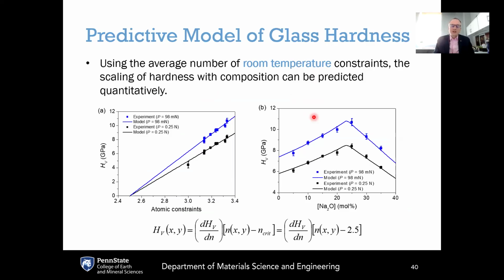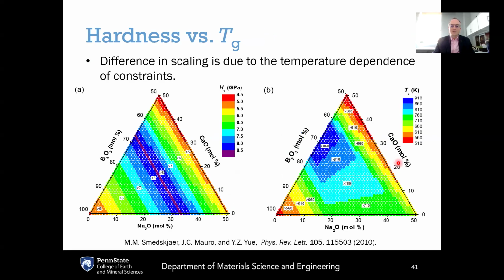This shows the evolution of glass hardness, where the glass hardness is proportional to the number of rigid constraints at the temperature where the hardness is measured, which is usually room temperature. This plot on the left shows a linear relationship between measured hardness and the number of atomic constraints per atom. And if you change that x-axis to be a compositional axis instead of a number of constraints, you can see that this captures the boron anomaly with respect to hardness, where you've got an initial increase in hardness. As you get more tetrahedra, that increases the connectivity of the network as there's more rigidity until it peaks where the number of tetrahedra peak, and then the hardness goes back down where non-bridging oxygens start to form.